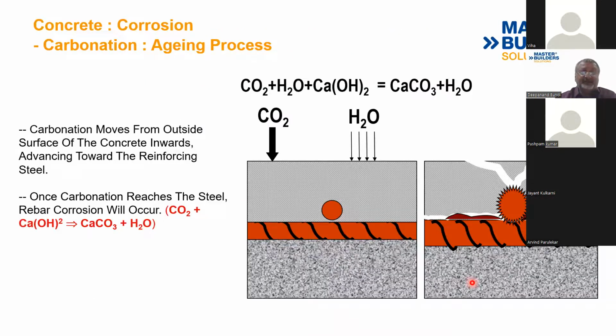Then we have carbonation. Carbonation, if I get time, I will cover in the next capsule. Basically, carbon dioxide is there in the air. We all know it's about 0.04%. And this carbon dioxide, when it reacts with H2O, forms H2CO3, that's carbonic acid. That carbonic acid reacts and combines with the calcium hydroxide and turns it into calcium carbonate. Now, this calcium carbonate, when it is formed, reduces the pH of the concrete. And when the pH of the concrete is reduced, the corrosion process is accelerated.